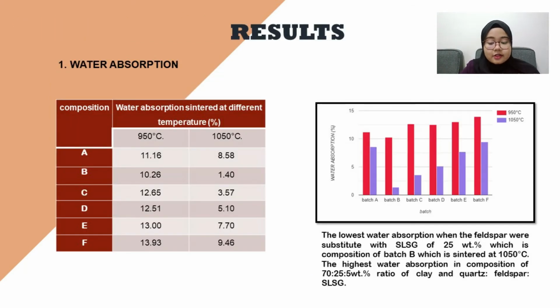Next are the results of this study. The analysis that has been done for the samples is physical analysis, which is water absorption, porosity, bulk density, and linear shrinkage. So here is the result for water absorption. The lowest water absorption is when the feldspar was substituted with SLSG of 25 weight percentage, which is the composition of batch B, sintered at 1050 degrees Celsius, and the highest water absorption is batch F, which is sintered at 950 degrees Celsius.